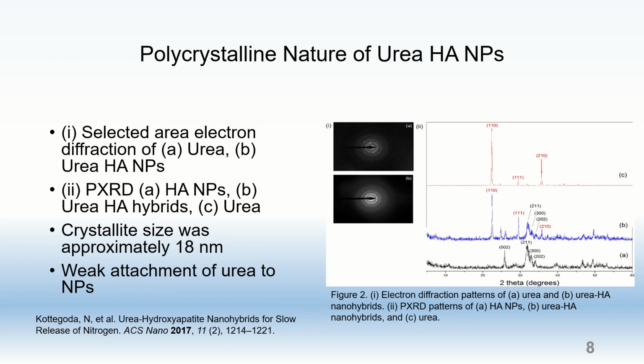Also, there were no observable shifts in the PXRD peak positions before and after the surface modification of the hydroxyapatite nanoparticles. And what this indicates is that the attachment of the urea to the nanoparticles is weak and does not substantially modify the hydroxyapatite nanoparticles.